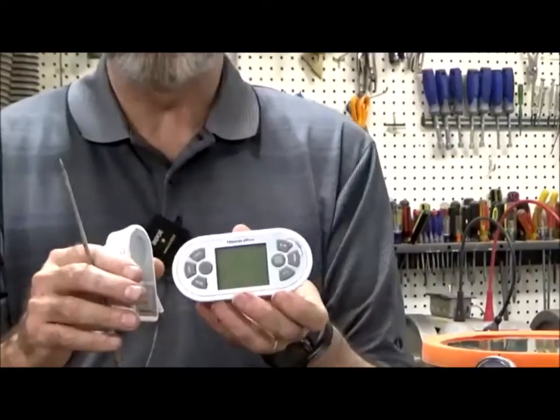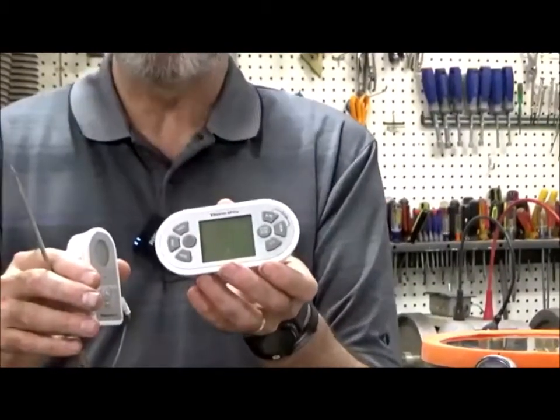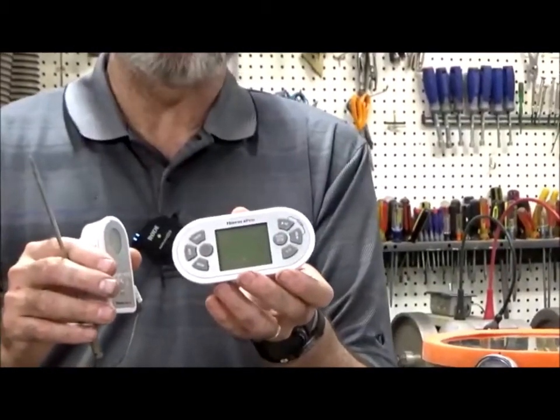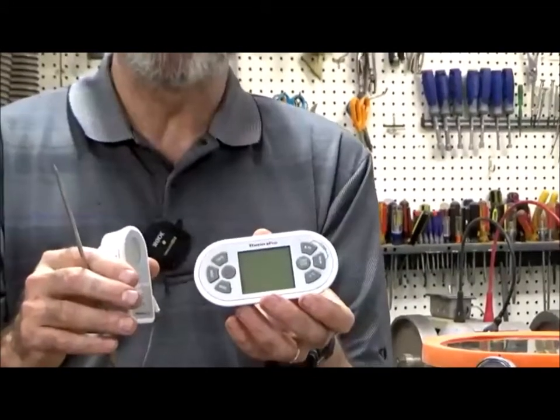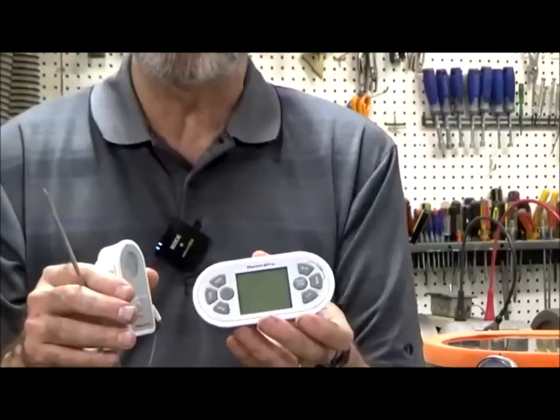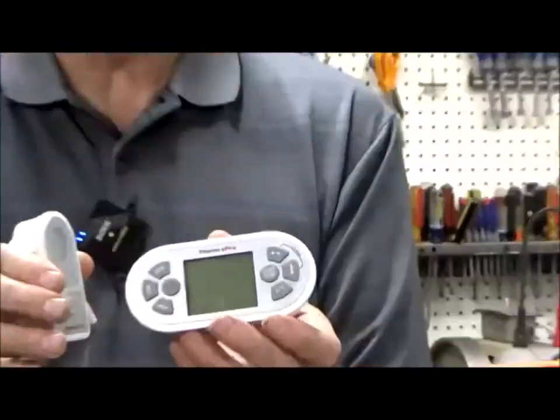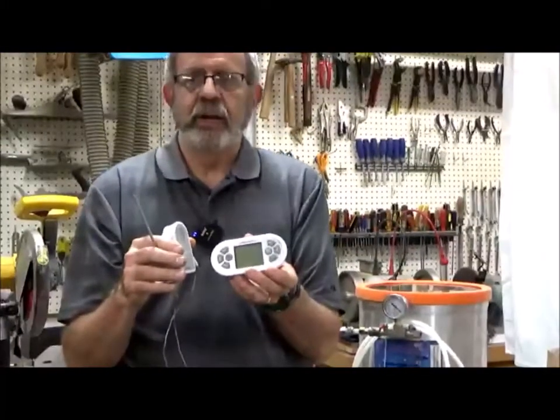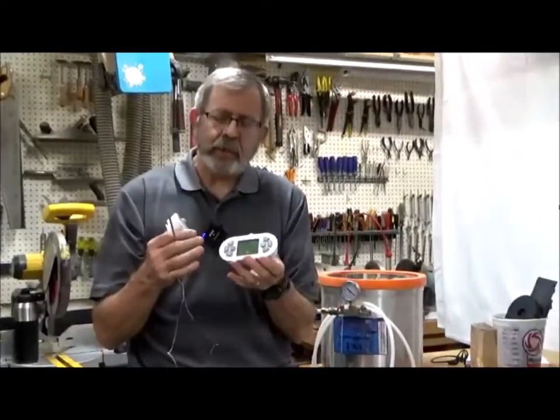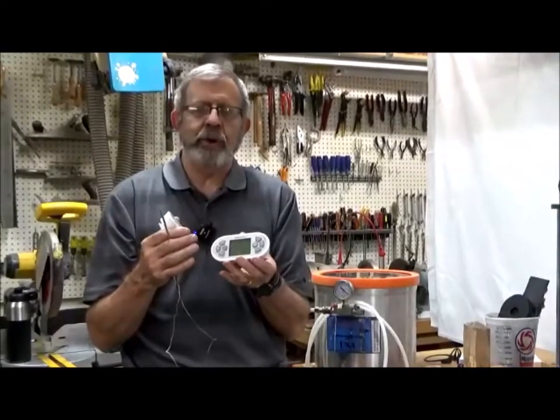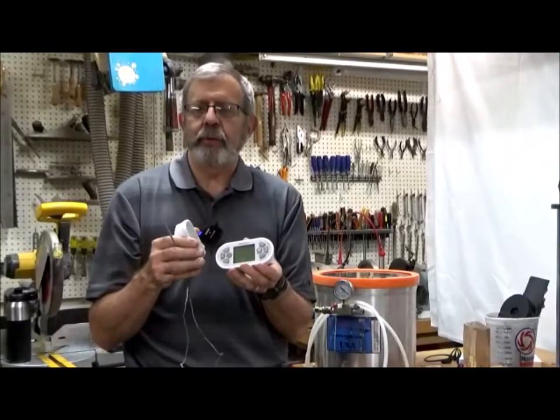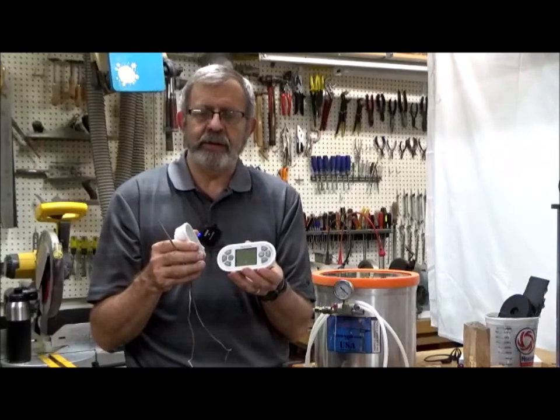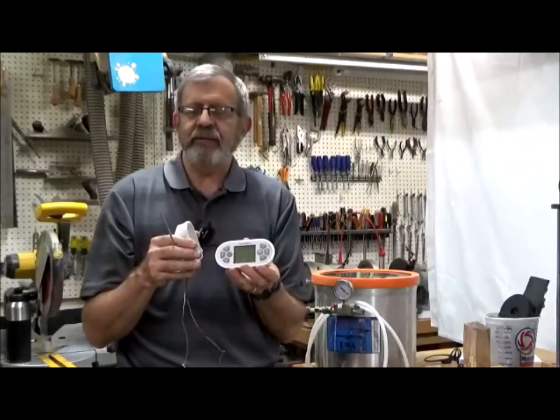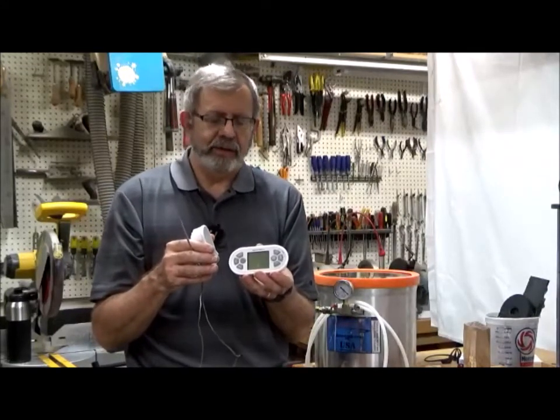So I can bring the remote back into my shop, and I can set it for a temperature. So I have it set for 210 degrees. And if the oven should go above 210, it alarms and tells me that. And I can go out and make the adjustment outside. Because if it gets too hot, like I said, it just evaporates all the resin out of the wood before it has a chance to set in there. And then now you have an expensive puddle in the bottom of your oven.